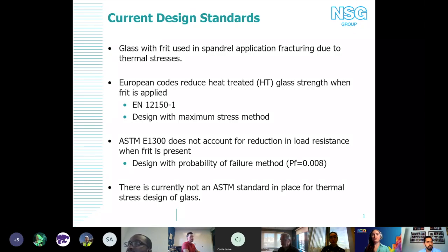One of the main differences between the two standards is that in the US, we design using a probability of failure method. So it's acknowledging that there are inherently critical flaws on the surface of the glass that can cause it to fail below whatever the maximum principal stress in the glass is at the time. Once the glass comes off the line and starts being processed and washed, you start gathering these little flaws called Griffith flaws on the surface of the glass, and they become locations for concentrated stress, essentially.